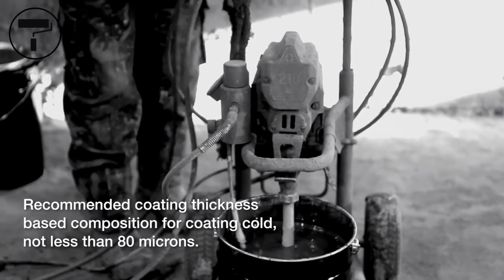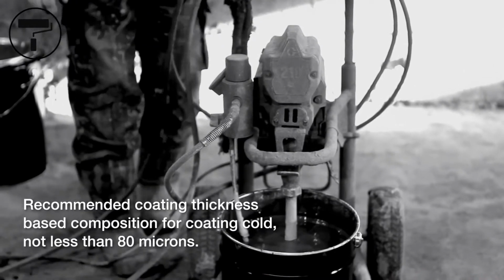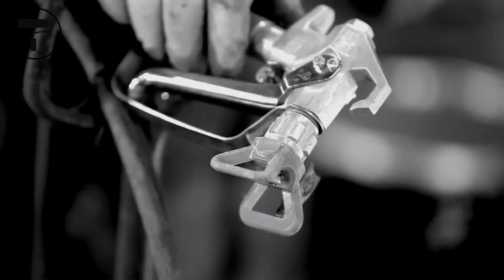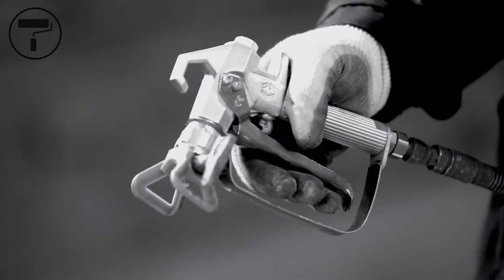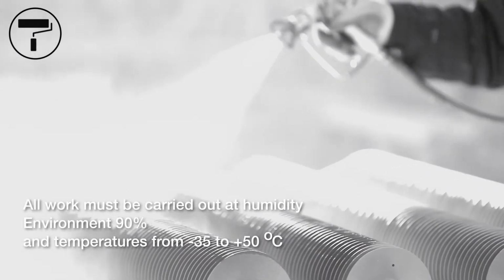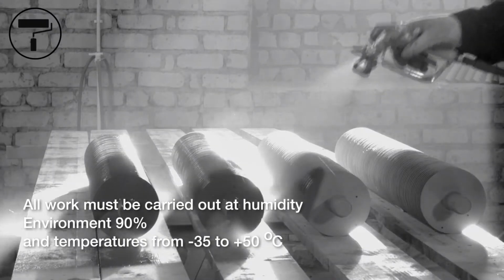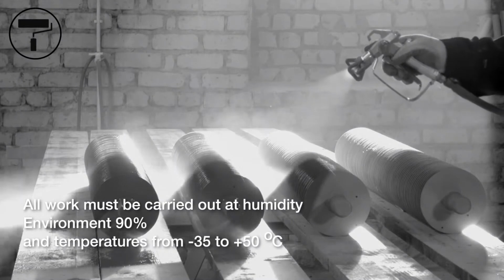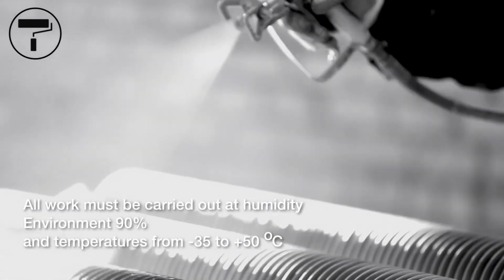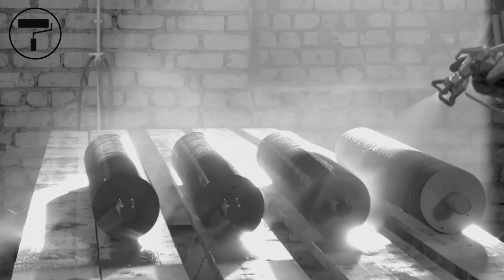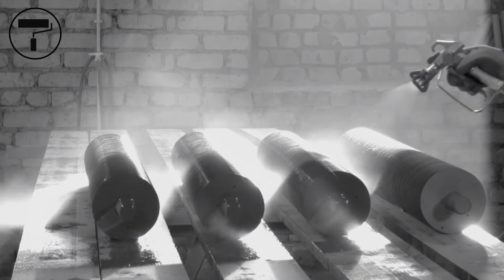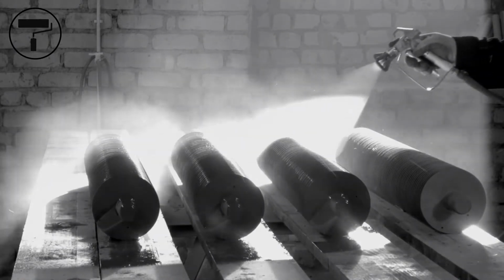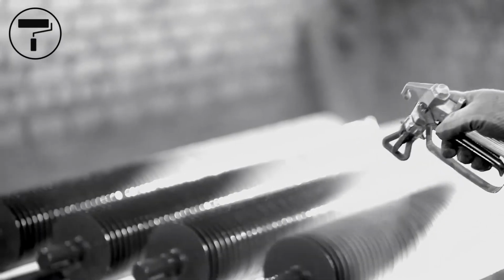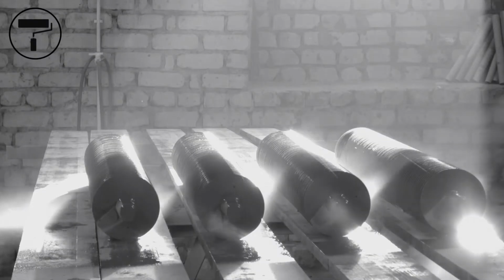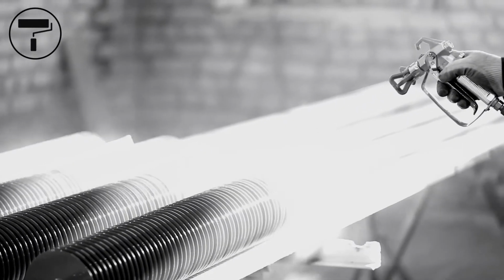The service life of the finished coating depends on its thickness and the extent of the corrosion aggressiveness of the environment. Recommended thickness of the cold coating composition is at least 80 micrometers. When applying a protective zinc coating, all work must be conducted at ambient humidity up to 90% and a temperature from 35 degrees below zero to 50 degrees above zero.